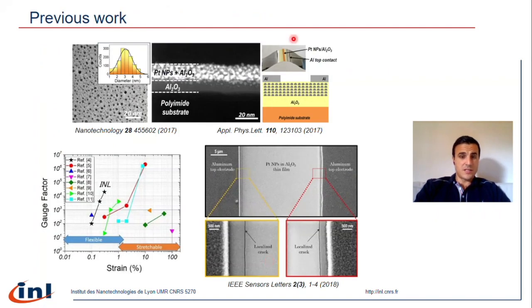As you can see on this slide, we have developed a nanostructured thin film by using atomic layer deposition. We have developed some thin film integrating platinum nanoparticles encapsulated within alumina. Thanks to this nanostructured thin film, we could generate cracks with small asperities and low dispersion on the size of these asperities. Thanks to that, we could get giant gauge factors at low strain level, gauge factors which were at the state of the art at the time.